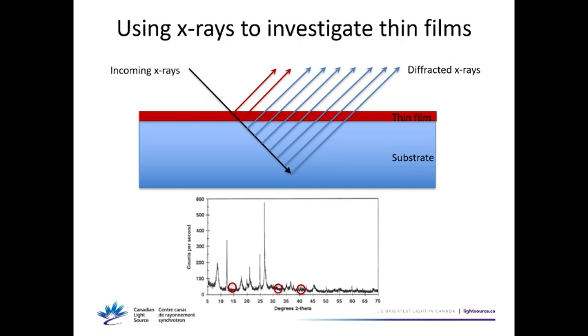In his case, it was the beam size related to the single crystallite size in the sample. For a thin-film, let's suppose we come with hard X-rays and want to investigate this red film on a blue substrate. With steep incidence and an attenuation length comparable to this arrow, most of the signal we measure will come from the substrate — not what we're interested in. The thin-film information is buried in the noise. So this is not an effective way to investigate the thin-film.